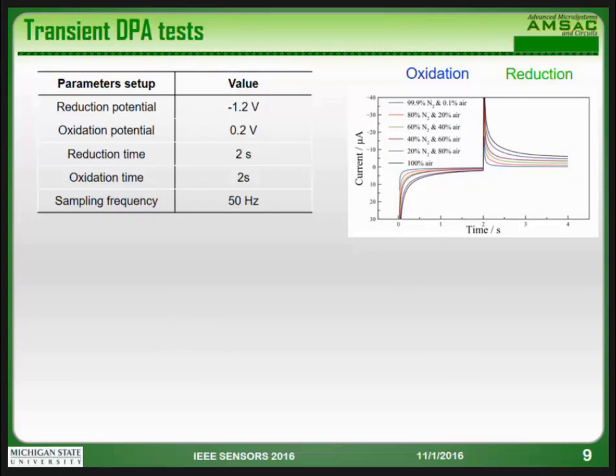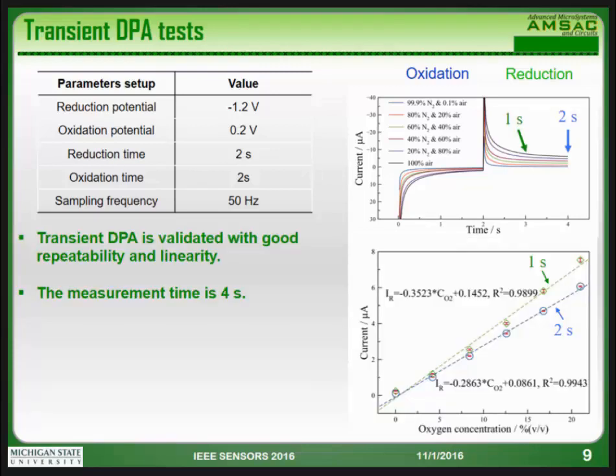Okay, here shows the parameter setup. We optimized the different parameters here, and then we performed the test. From this test, we can see that the sensor responds differently to different concentrations of oxygen. Then we extracted the current at 1 second and 2 seconds, and we made the calibration, and it shows very good results. We performed 5 repeatable tests, and here shows the error bar. The repeatability is very good, and the linearity is also very good.